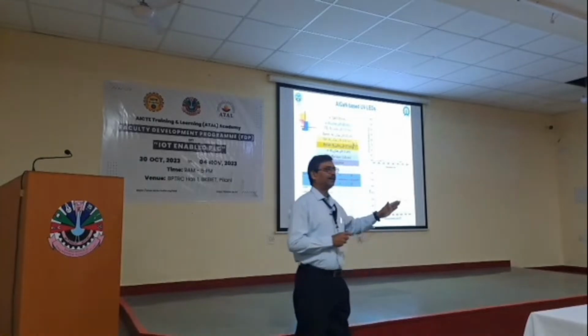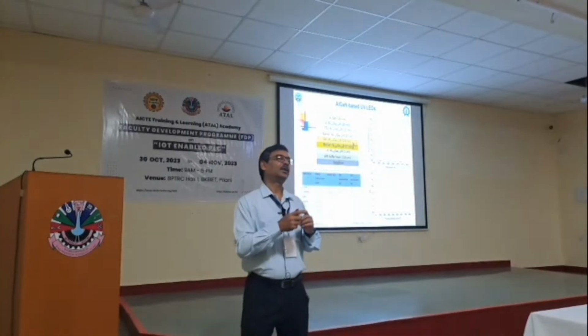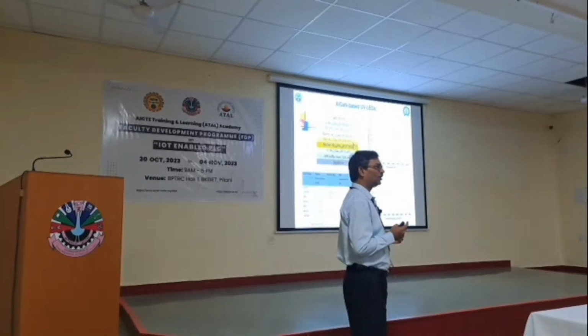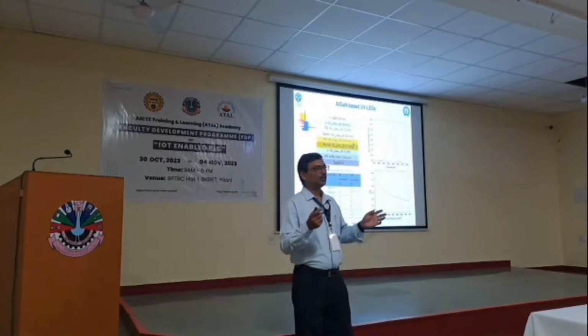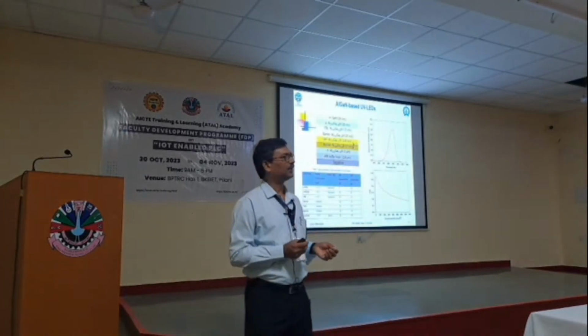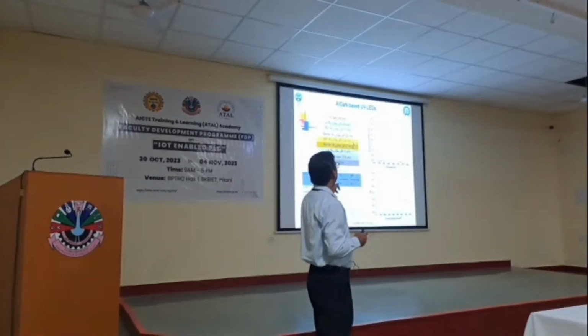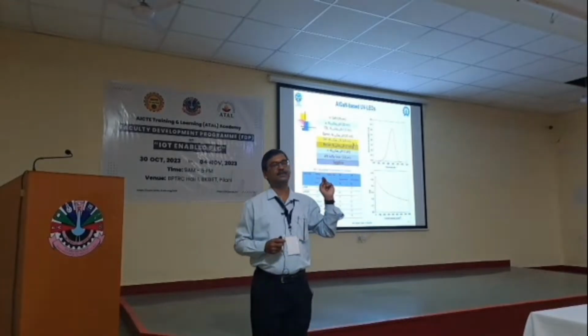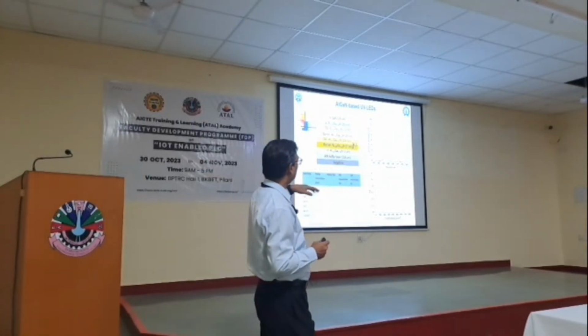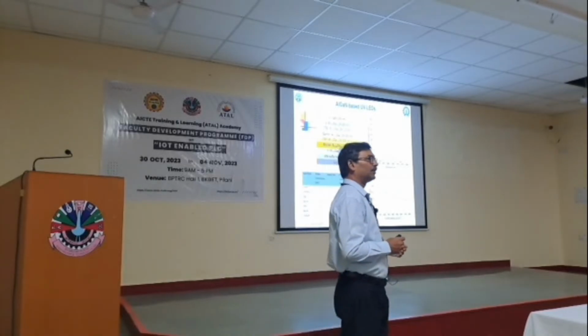So we first fabricate the blue LED, and then we mix yellow phosphor with some elastic material, that is polymer, with uniform composition, and we deposit it on top of that. And what emission are we getting? White. So it is everywhere. So that is the blue and white LED. And this UV LED is for aluminum composition. With different aluminum composition, we can change the emission wavelength.